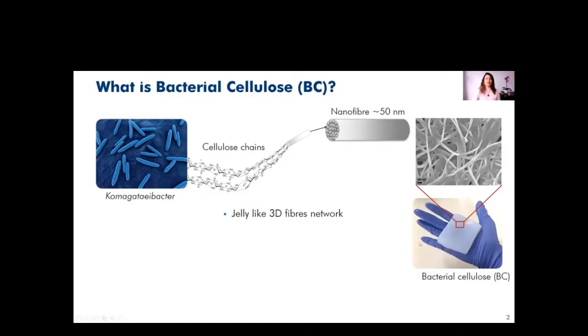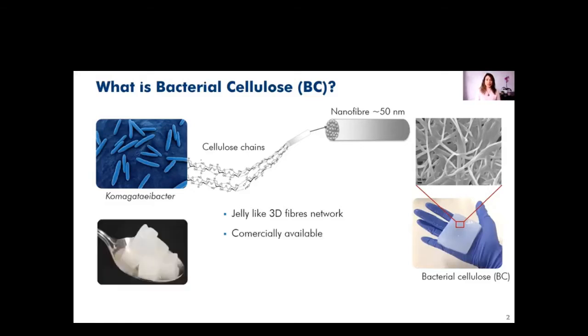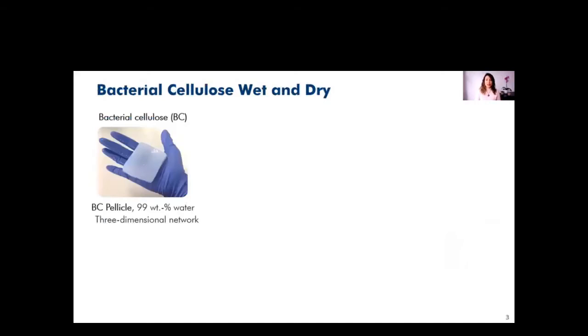And the visual appearance of bacterial cellulose is like a jelly-like 3D fibers network. Bacterial cellulose is commercially available, it's just like nata de coco, and it's also chemically pure. It has high crystallinity, approximately 90%, and the BC single fiber shows a modulus of 114 gigapascals. When bacterial cellulose is wet, it contains approximately 99% of water, and it's like a BC pellicle.